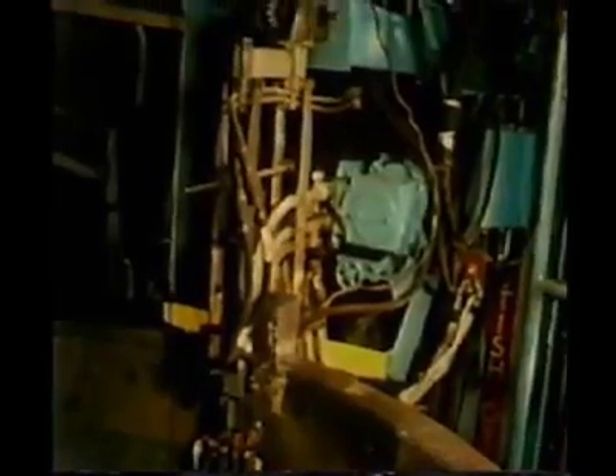The precautions we used to take against distortion and shrinkage, like turning the work over and over, aren't needed anymore. All we have to do is set up the plates with a predetermined distortion allowance, and the final dimension will be accurate. It's a good weld, too. Nicely even, with no cracks and no porosity, and slag inclusions no longer worry us. Versatility and economy in vertical welding are the great attractions of electro-slag welding from my point of view.